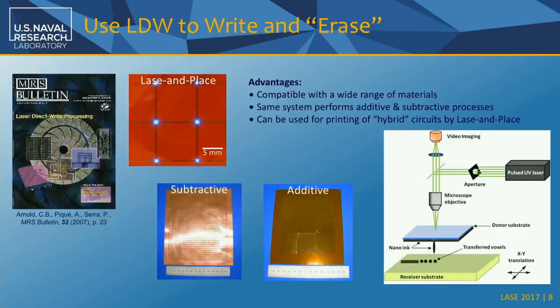So through the years, what we have shown is that with the laser Direct Write, we can do both addition of material and also remove material. And that is what, in my opinion, gives these laser-based techniques an edge. Because you have the same tool, the same setup, and it lets you do two things that complement each other. I like to think of it as writing and erasing. So if you make a mistake, you can come back and trim your pattern. If you need to drill a via to connect between two levels, you can do that with the laser.